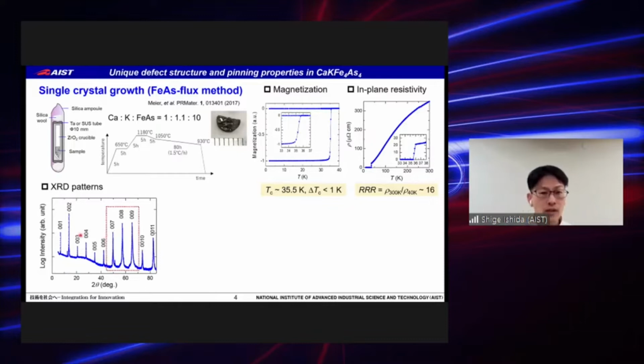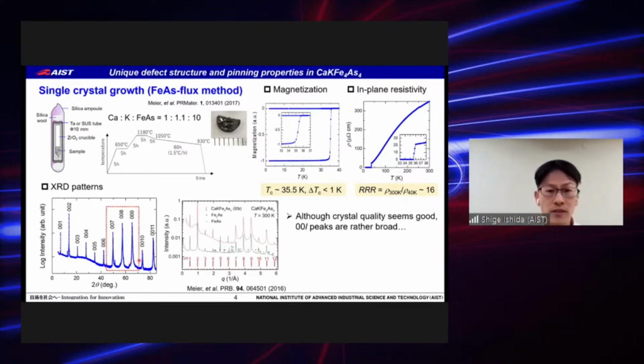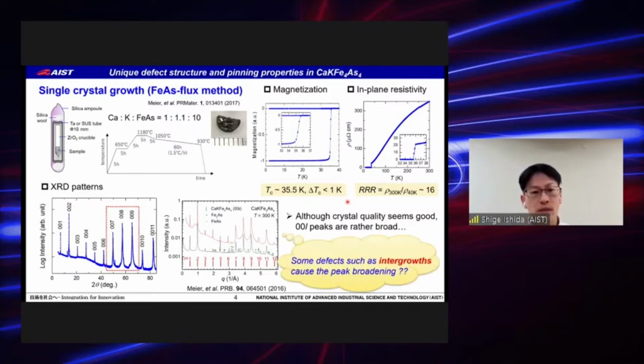However, you can see that the 00l peaks at higher angles are rather broad, and such feature can also be seen in previous works. So although crystal quality seems good, the 00l peaks are rather broad - this may indicate some presence of defects such as intergrowths, which cause the peak broadening.